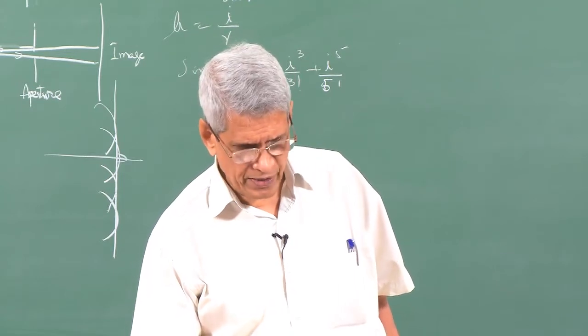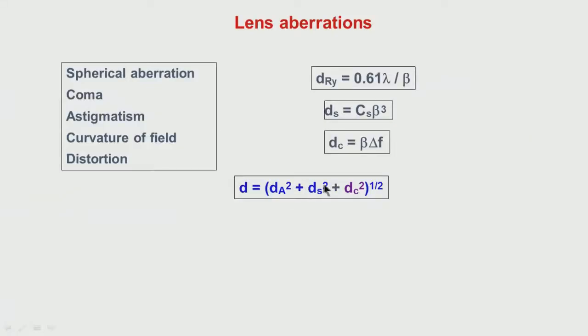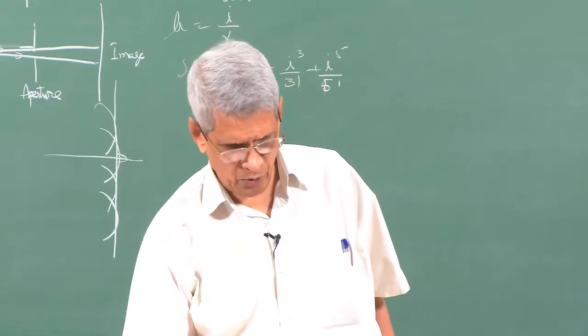So d equals the square root of dA squared, plus dRy squared, corresponding to the Rayleigh criterion, plus the spherical term, plus this which is due to chromatic. Since chromatic comes from the non-monochromaticity of the beam, we assume that we are able to make a beam perfectly monochromatic.